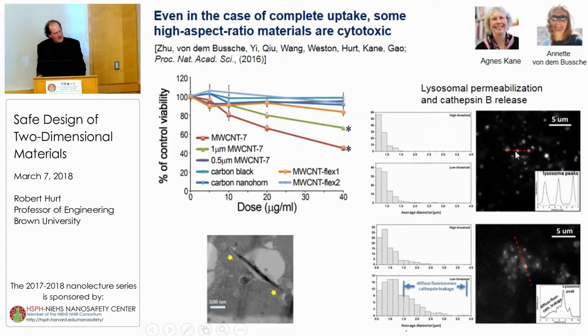And so there was some reason to think this had to do with lysosomal disruption. And Agnes and Annette have this assay that looks for the release of cathepsin B, which is a protease inside lysosomes. And if a lysosome is damaged, it gets out. This particular protease keeps its activity at the high pH in the cytosol. So it wreaks havoc inside the cell once it gets out. And it's a very important target for these toxicity studies.